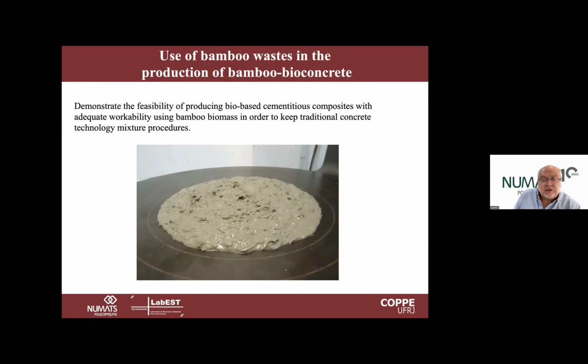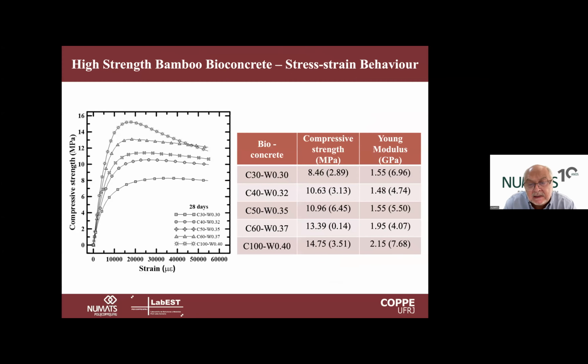So we have a material that can have up to 7% of biomass in the composition. We also replaced a lot of cement. In some mixes, we had up to 70% cement replacement. This is done so we can reduce the emissions of the cement, because then we use pozzolanic materials. Both materials we use from bioash, rice husk ash or metakaolin, to replace cement in this proportion.